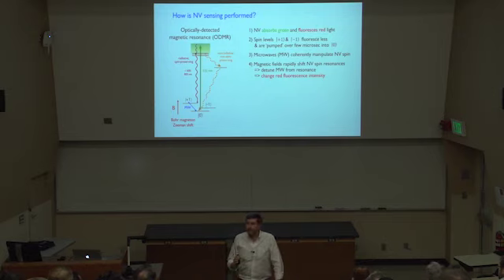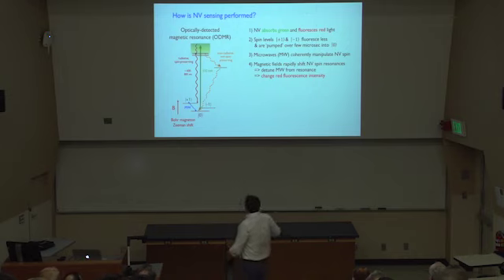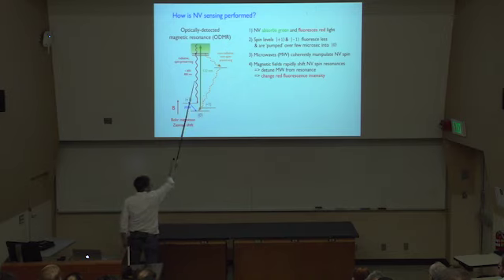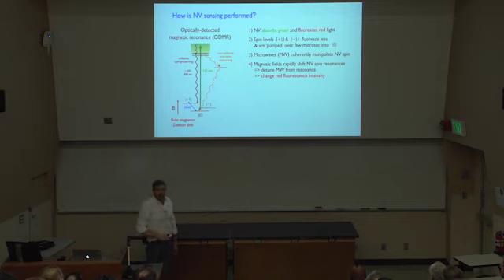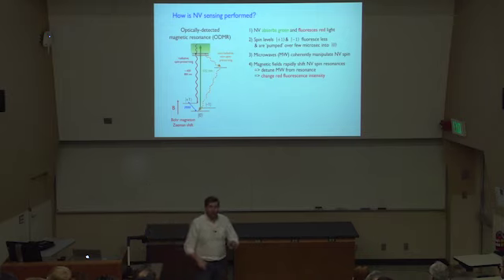Green in, red out. Its spin state won't change, and all it does is fluoresce. If you're in ms equal plus or minus 1, you'll absorb a green photon, and with approximately 50% probability, you'll either fluoresce with a red photon back down to the state you started in, plus or minus 1, or you'll non-radiatively decay slowly to ms equals 0. So there's this fluorescence time of about 13 nanoseconds, and this radiative decay time of approximately 300 nanoseconds. So in the early stages, when you turn on your green light, you're going to have a photon flux that's going to be different between ms equals 0 and plus or minus 1.